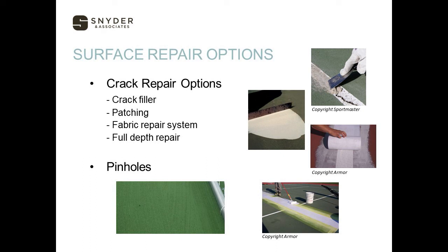There are also a lot of calls about pinholes that show up in the surface. A lot of these pinholes are a reflection of the surface below — if it's a coarse surface rather than the smooth surface specified, some pinholes will show up when you start putting on the paint surface. They also appear during hot weather applications when water evaporates out of the surface a little quicker than it should, creating pinholes. It's something we need to be aware of during construction.